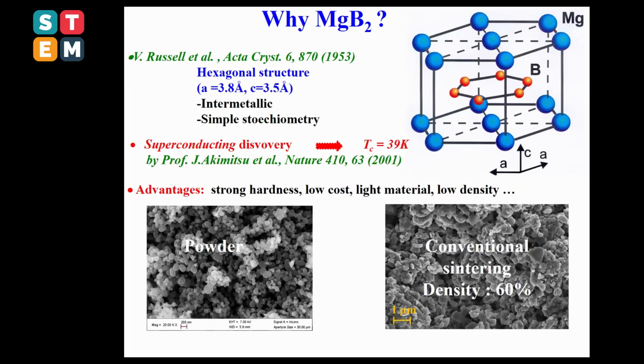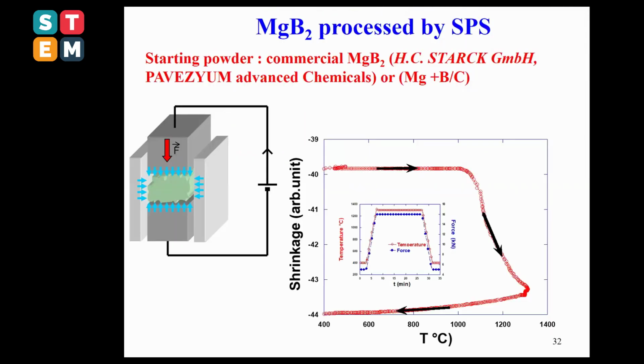But when you observe the powder in these two figures, I show the initial powder, and when you compare with the conventional sintered MgB2 materials, the density is quite low. That's 60% only. This is why the main thing is, by using SPS, to densify this material, to increase the